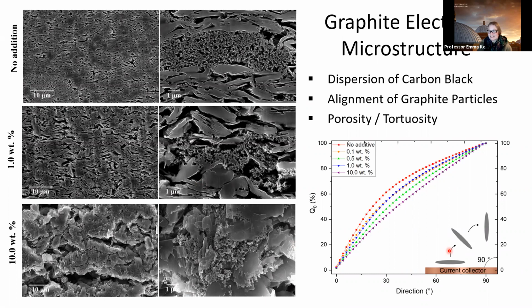So we still have to find some way of being able to improve the electronic conductivity, whether that's through calendaring or through another method, and reducing the porosity to get it to be a working electrode. I think this was very much a proof of principle to show that we could change the microstructure by using different secondary solvents and quantities of secondary solvents. But there's still a way to go before we understand it well enough for it to be a